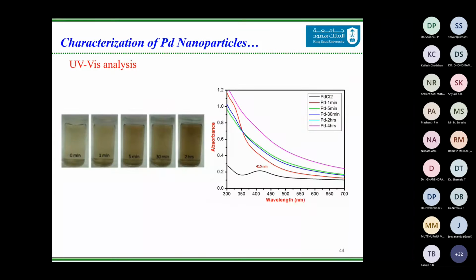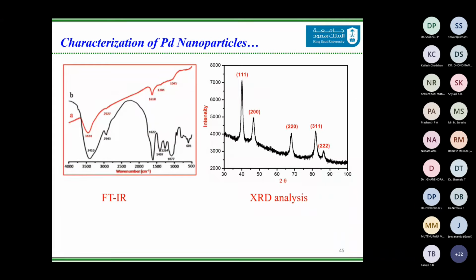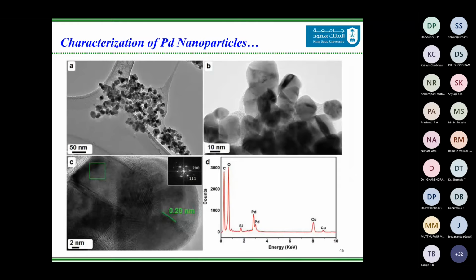And what we have observed is within 2 hours of time, we were able to see to it that this palladium chloride or palladium ion was totally reduced to palladium 0. And as I mentioned earlier, Polycarya has played a dual role in this regard also, where it has worked as a stabilizing agent as well as a reducing agent. And the palladium nanoparticles were confirmed by XRD. This is the 10 nanometer scale that we obtained, and you can see that these particles are in the range between 10 to 20 nanometers, and we don't see much of an agglomeration in this regard.